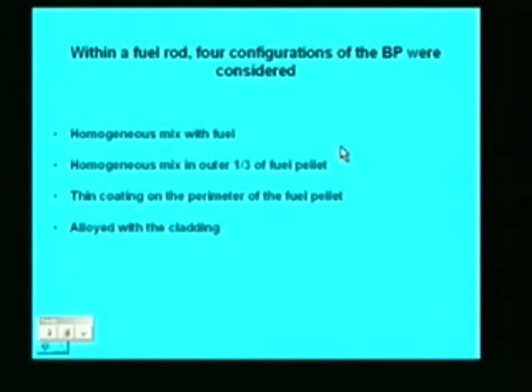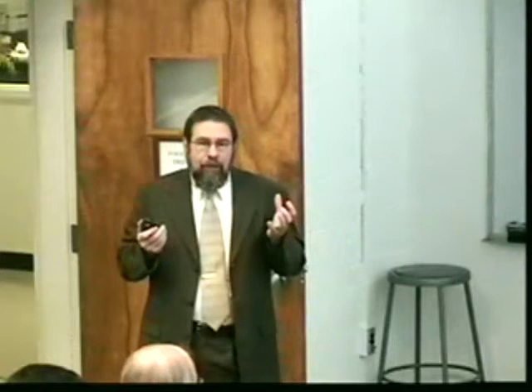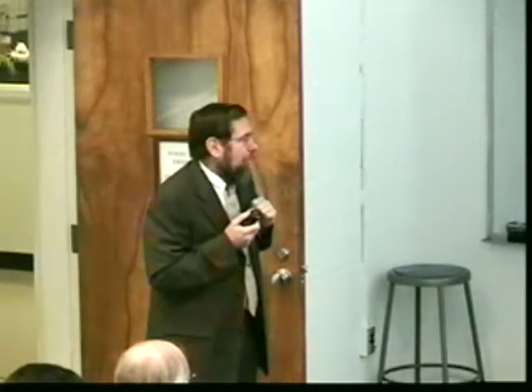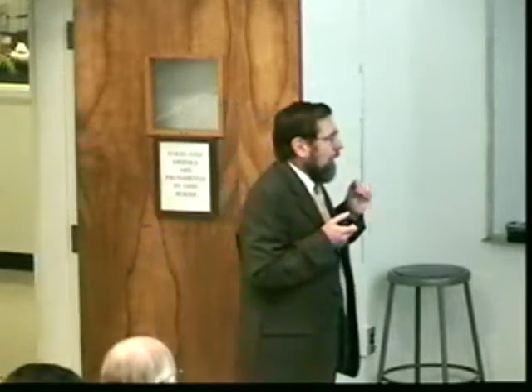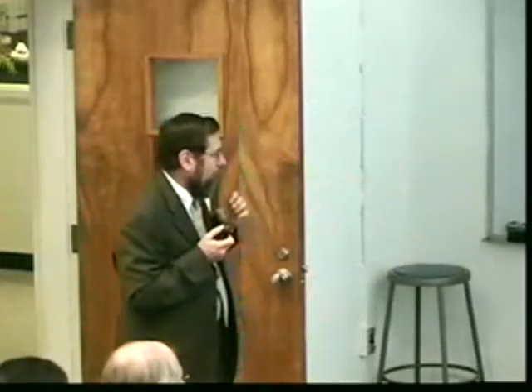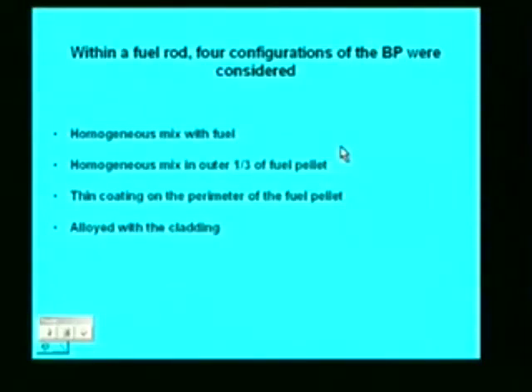Within a fuel rod, 4 configurations of the burnable poison were considered. One is simply to blend the burnable poison with the fuel. The other is to put the burnable poison only in the outer third of the fuel pellet. And this can be done. It can make compound fuel pellets. Another is to have a thin coating on the perimeter of the fuel pellet. It's done in Westinghouse fuel. It's the burnable poison on the fuel, a coating. Another idea, which I think is fairly new, is to alloy the burnable poison element with the cladding. So in this case, we'll use the burnable poison in a metallic form and alloy it.